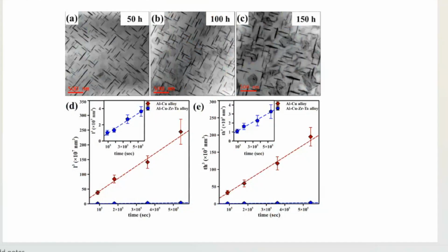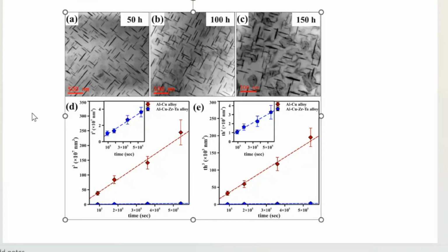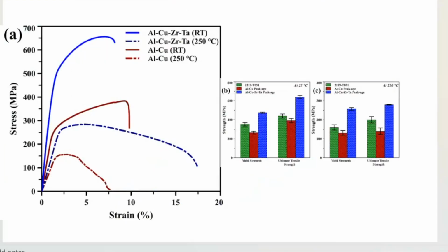We looked at the coarsening rate of these plates with the tantalum. And you can see that there is virtually very little coarsening with time. These are actual experimental measurements, whereas aluminum copper alloys coarsen very rapidly. And this coarsening stopping is because of, now we conclusively prove that it is because of tantalum segregation at the tip, the growth tip of the plates. And because of this, you get a very high strength at room temperature.